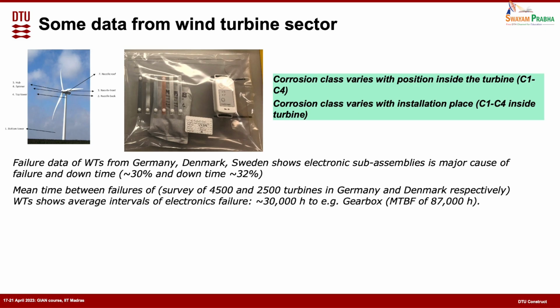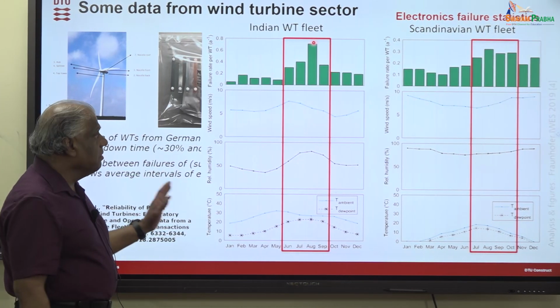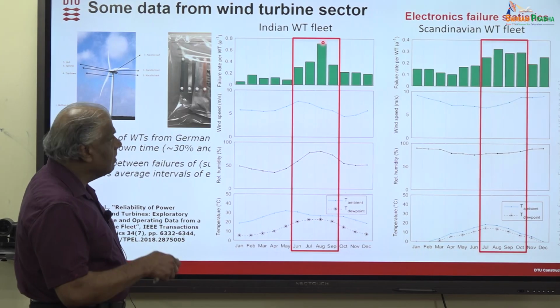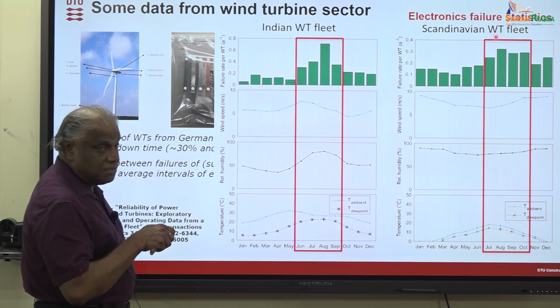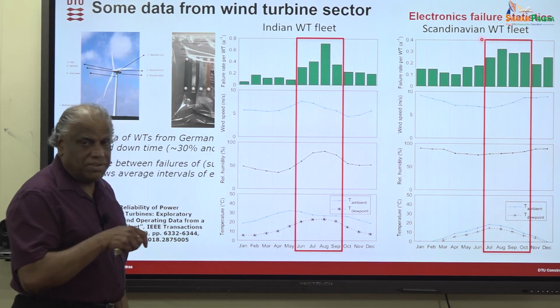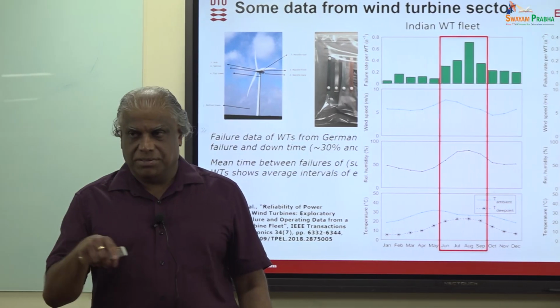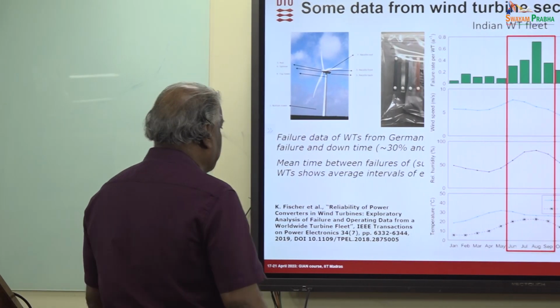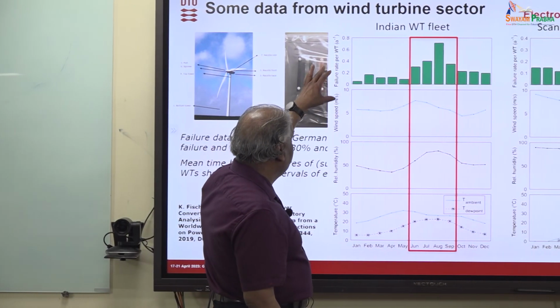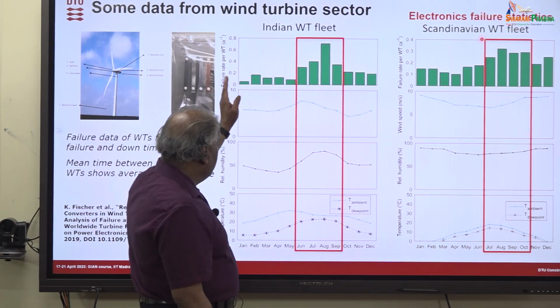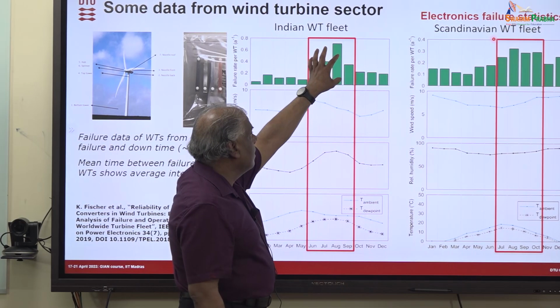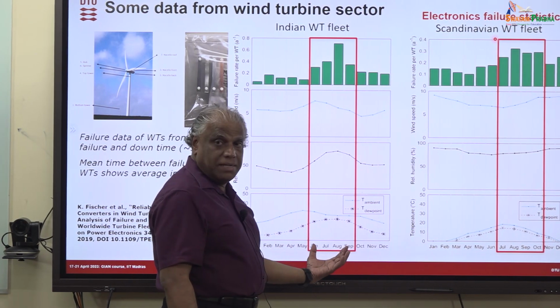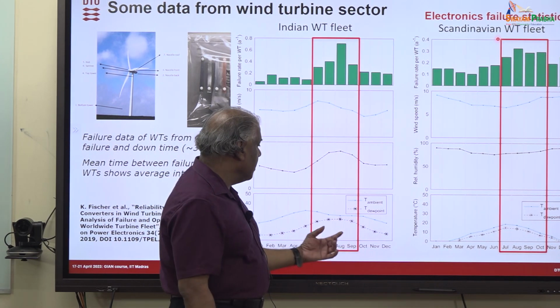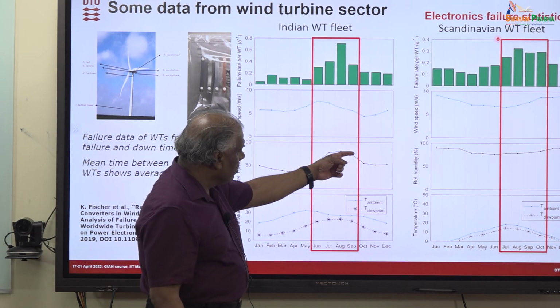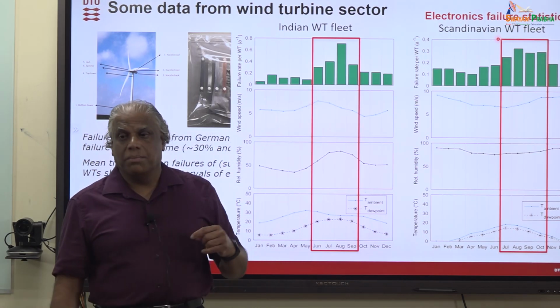But to show you a little more, the Fraunhofer Institute in Germany has done very nice investigations all over the world, but I am showing here the Indian wind turbine fleet and the Scandinavian wind turbine fleet. Scandinavian means the combination of Denmark, Sweden, Norway and Finland. If you look at this failure statistics, the failures per wind turbine occur all over the year, but the number of failures is higher during this period, which is also a period with higher humidity. You can see the relative humidity is also higher during that period, and that is when you get a much higher number of failures.